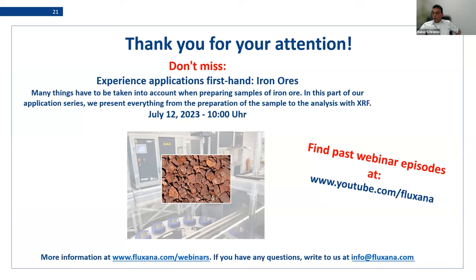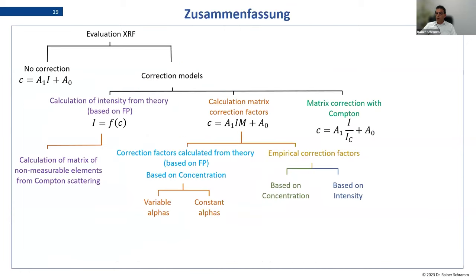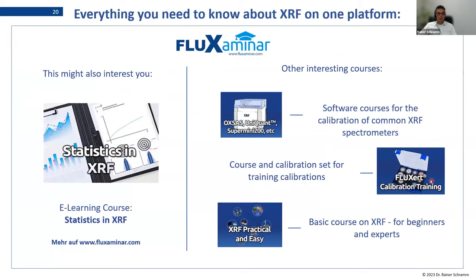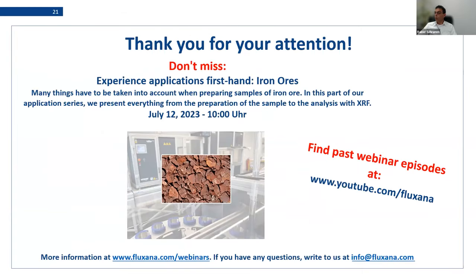So then there's another question. Could EDXRF use these correction methods? Yeah. So the correction methods are independent of energy dispersive or wavelength dispersive XRF. There is no difference what technique you're using. In the end, we have an intensity and we are looking for a concentration, and the effect between both is X-ray fluorescence. And this is just described by the same theory. There's no difference between energy and wavelength dispersive. So any more questions?